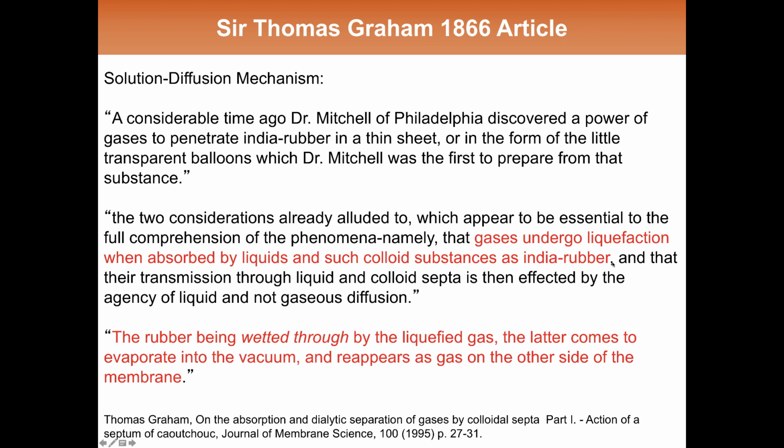So it's known that gases, when they dissolve in liquids, exist in an environment that's a liquid-like density. And so he's postulating here that gases condense and liquefy essentially when they dissolve into a material such as India rubber. And this is the solubility step in the solution diffusion model.